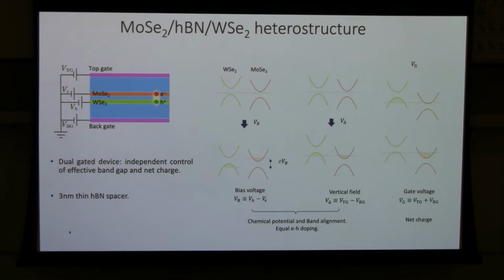So if we add the electron and hole in the system, one question is, how do we characterize them? One thing with this interlayer electron-hole bilayer is that they live for a very long time. That means they don't emit and they usually don't absorb light effectively. So we can't really use, say, photoluminescence of this interlayer exciton to probe them. So what we do instead is probe the behavior of the electron and the hole separately through optical spectroscopy.